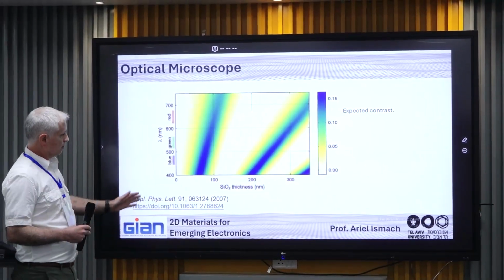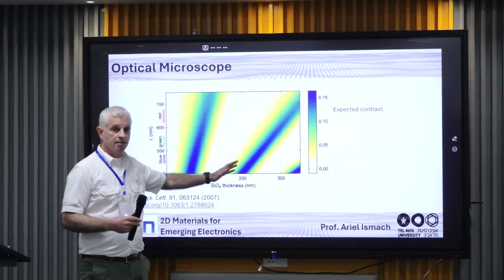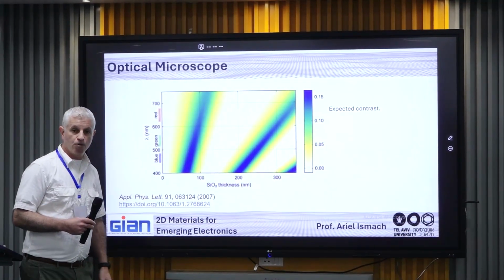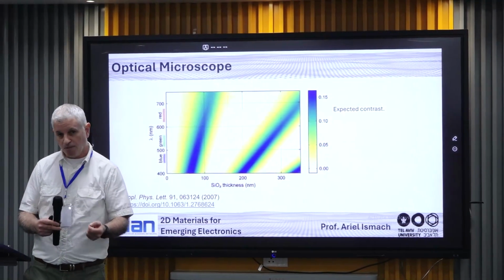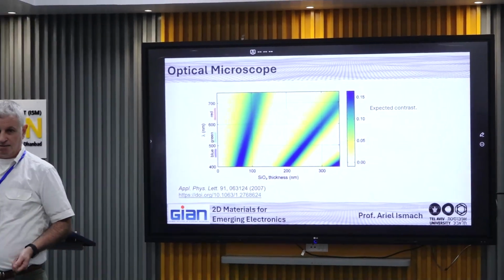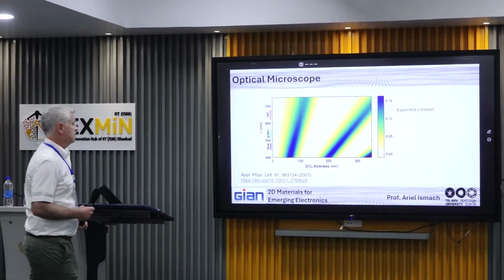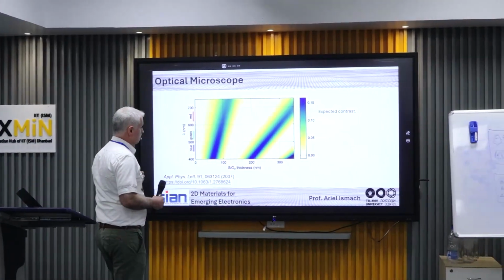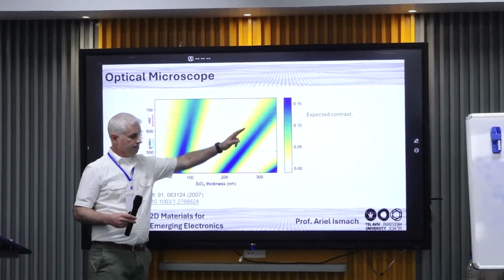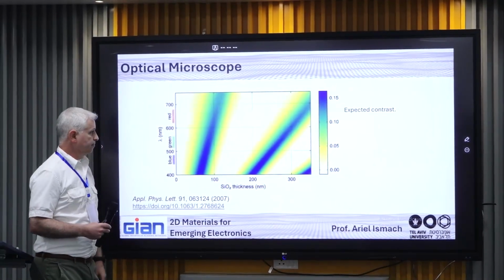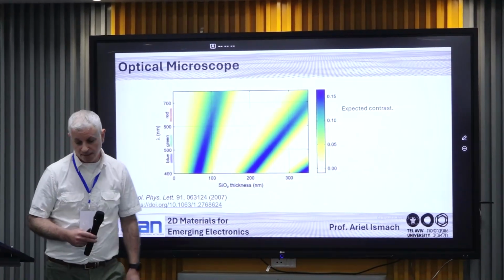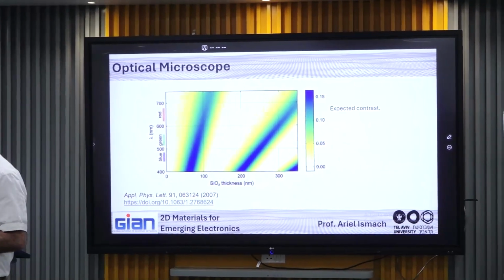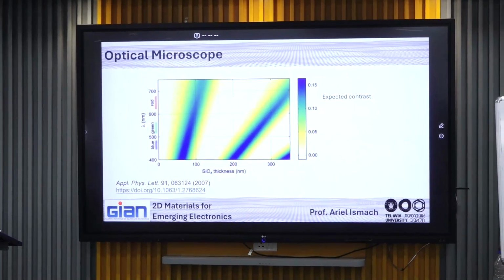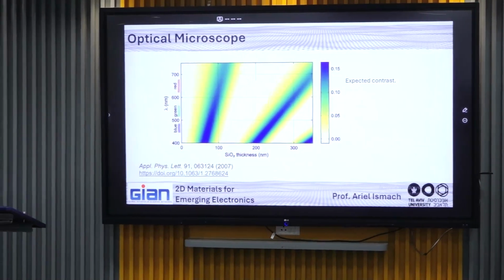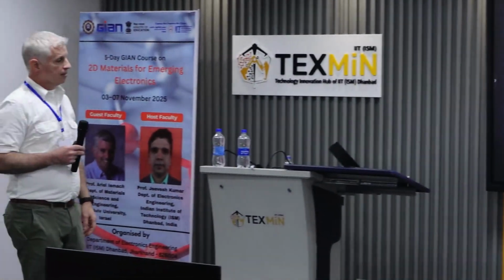And as you see, there are very specific places where you have a good contrast. Now, a good contrast is the one that will allow you to identify the layers, to see the layers. Okay? And that's why it's very important to be on one of these lines in order to make an easy identification after you exfoliate your material. And the same works for many other 2D materials, very similar.